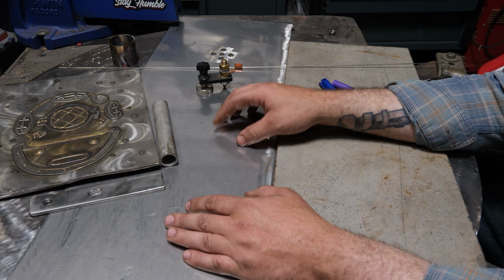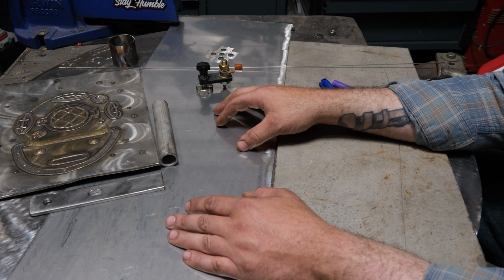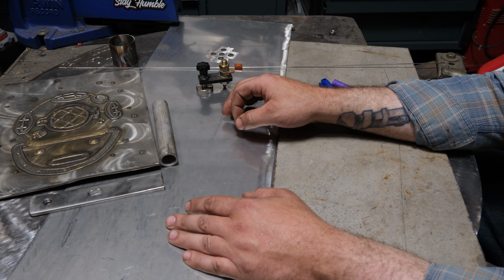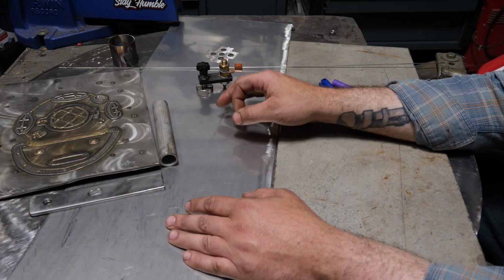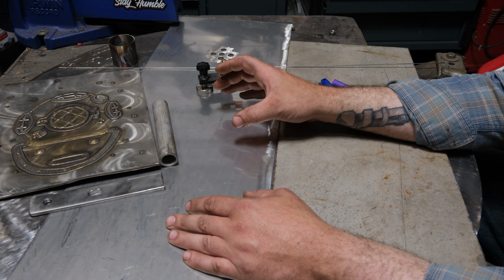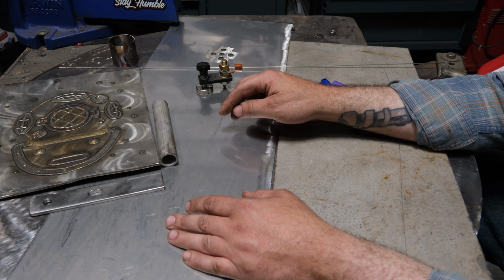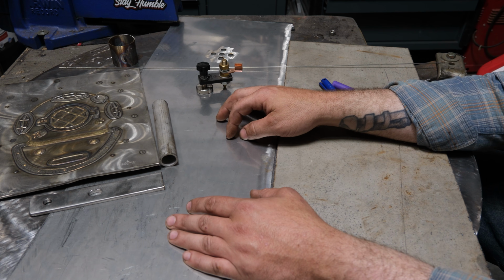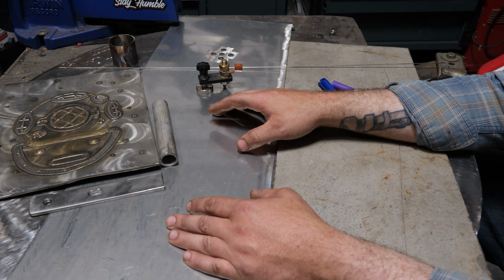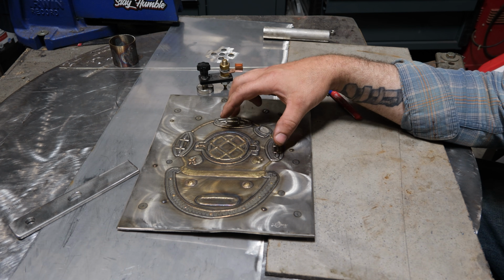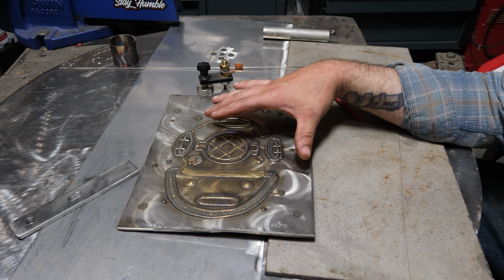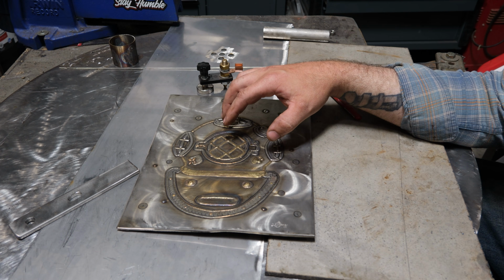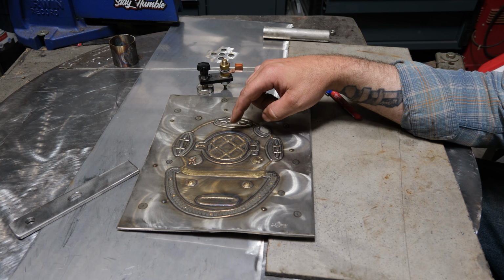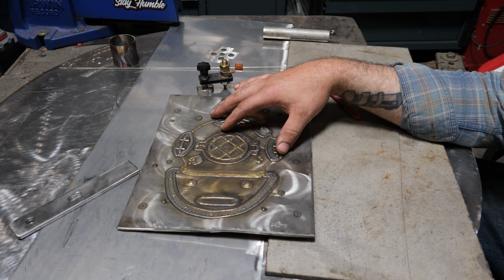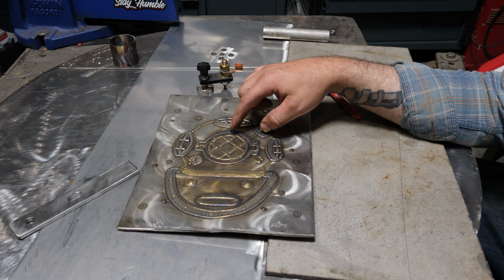What gives it its stainless or its resistance to rust is that chromium and that nickel. Well, when you weld it and you don't have adequate gas coverage, what ends up happening is that red hot metal that you just welded oxidizes in the air, and then it loses its corrosion resistance due to all that oxidization. Now, there's two distinct problems regarding that stainless steel faces. One is just straight oxidization. In this welding art piece I made, I used oxidization to create color to be able to make this art, right? So in this case, the oxidization is both desirable and it's what I'm trying to achieve. When you're actually welding things that need corrosion resistance, this oxidization is undesirable.